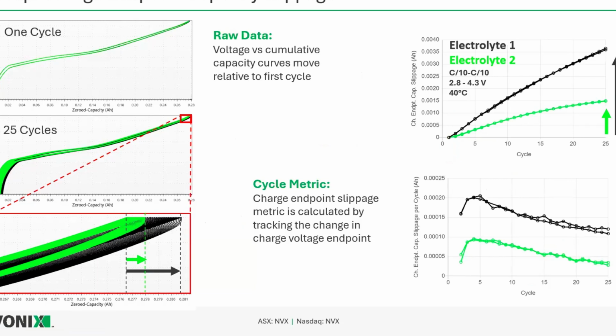What this means is if we charge our cell up and then discharge it down, we're not going to end up back at zero. And if we keep repeating this over and over again, we're going to surpass this endpoint, and our cumulative capacity curve is going to walk out to typically higher and higher capacities. And the rate at which it does this, if we're tracking electrons carefully enough, accurately and precisely enough, this rate that the curve walks out can tell us something about the rate at which those mechanisms happen.